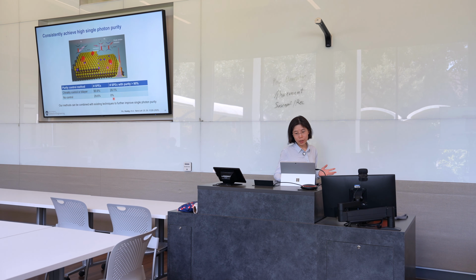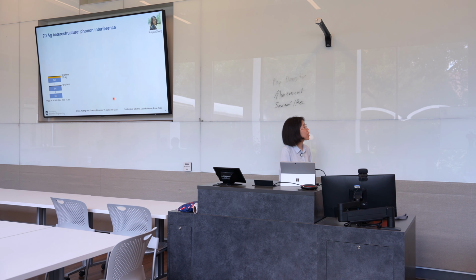So let me now switch gears a little bit and talk about phonons, and in particular, phonon interference. This is a very interesting phenomenon that we discovered recently, and we are looking at a very special sample called a 2D metal. The way we have these 2D atomic layers of metal is like this. You start with a material called silicon carbide, and then you heat up the silicon carbide. So silicon will sublime and form very thin layers of graphene on the surface of silicon carbide. This is a well-known technique to fabricate graphene. It's called epitaxial graphene.